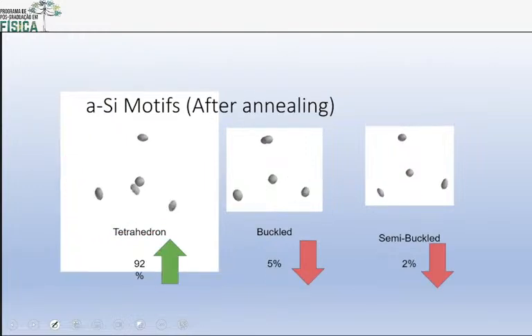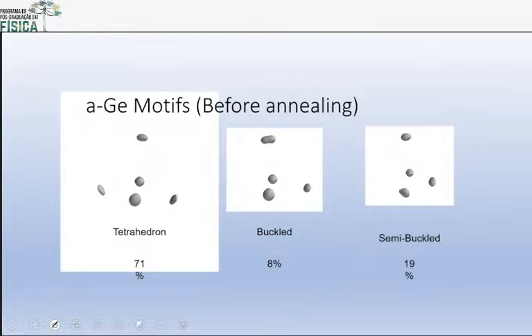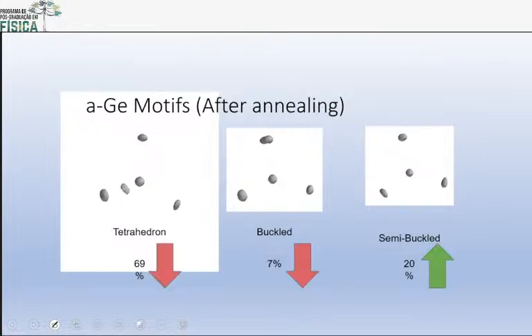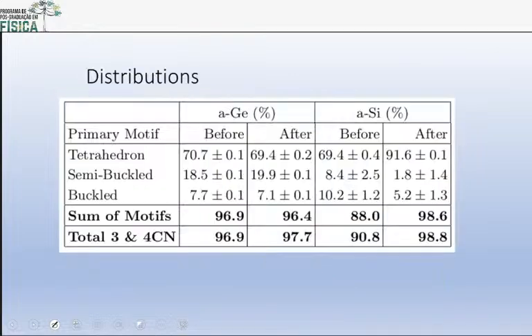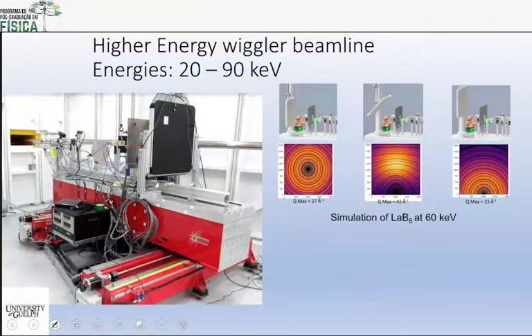And what we found is when we annealed the sample, that the ratios of these 3 different arrangements changed. So we were able to figure out what happens when you anneal silicon, right? That's sort of cool. And so we had to invent ways of being able to interpret our data. Okay, now I'm going to move on to another thing.